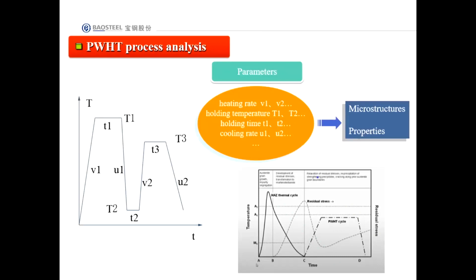Fifthly, a post-weld heat treatment process can be optimized. Which process is better can be found according to properties and microstructures by simulating different post-weld heat treatment processes using the Gleeble system. For example, we can design different simulation parameters, such as the heating rate, temperature, the holding time, and the cooling rate. For more accuracy, welding residual stresses can also be superimposed.